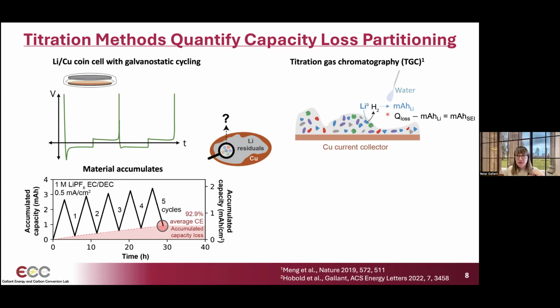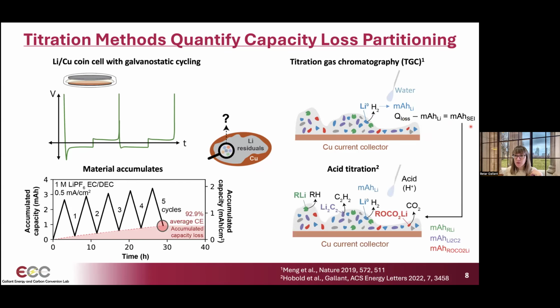I'll get a little bit more into that in a second, but they also assumed that anything not quantified and attributed to lithium zero must correspond to SEI. So you could estimate the amount of SEI remaining on the current collector simply as the difference between what the potentiostat measured and the dead lithium. Our group has been interested in expanding the ability of titrations to tell us more about the SEI composition.